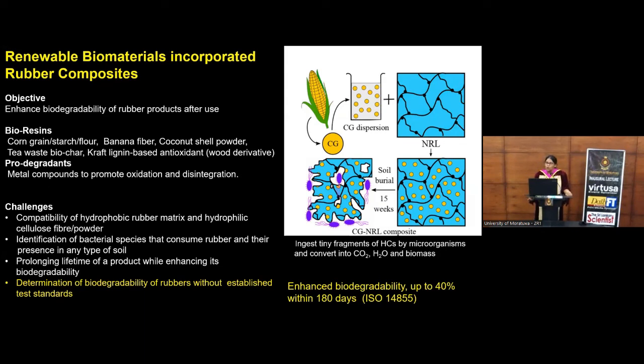Unfortunately, there are no international or national standards to measure the biodegradability of rubbers. We also have to use standards that are established for plastics, and this test is done for composting conditions and for aerobic digestion. Only 40% degradability is obtained within 180 days. But to validate the biodegradability of a product, 90% of the hydrocarbon has to be degraded within 180 days. But that limit is for plastics and not for rubbers.